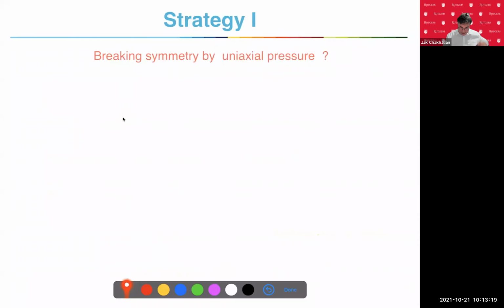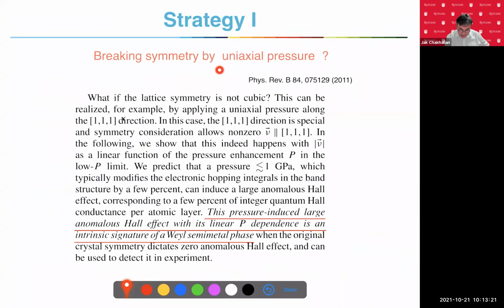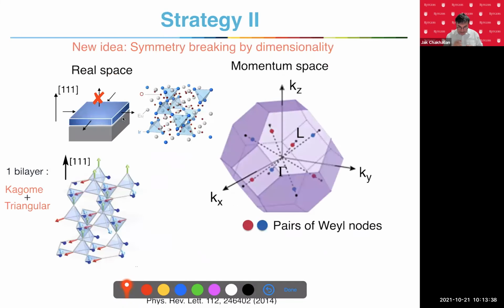People thought that's hard, and they said, well, why wouldn't you apply uniaxial pressure? Just break this cubic symmetry. And then maybe the special pair of Weyl nodes along this pressure direction will be revealed. People tried it, unfortunately, not very successfully. Another strategy was proposed by a Japanese group.